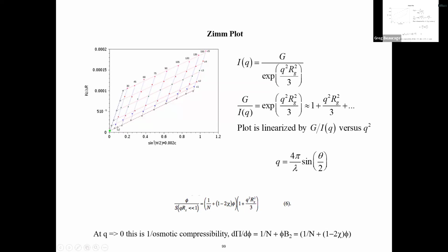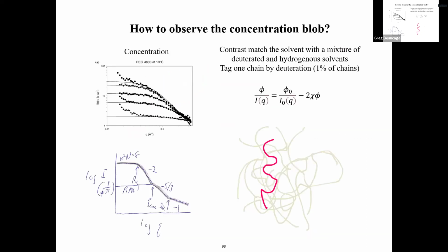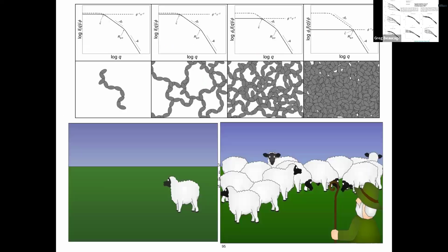And if you know the radius of gyration and the molecular weight, you can figure out how branched it is. Because you can say, well, if it was in a good solvent, you could predict the radius of gyration from the molecular weight, but it's monodisperse, right? But if it's branched, it would be a different number. So from using a light scattering detector and a GPC, you can get a lot more information. You can get information about each fraction that's coming off, like the structure of it. You get the absolute molecular weight, so you don't have to have a standard. And you also get this idea about what the thing is from it, so it's a useful detector to have. It's more expensive than an index detector, which just gives you the concentration.